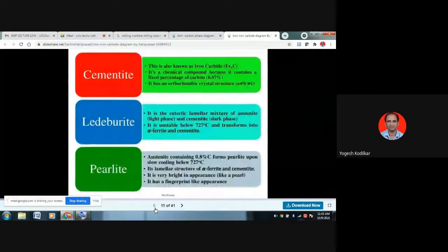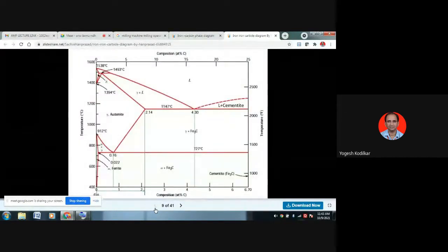This is the iron carbon equilibrium diagram showing different crystal structures. Initially, there is the alpha ferrite phase at 0.08% of carbon. Above 727 degrees Celsius and above 912 degrees Celsius, it is completely converted into gamma austenite. This alpha ferrite is in BCC structure, and at 912 degrees Celsius it is converted into gamma austenite. Above around 1490 to 1530 degrees Celsius, the gamma austenite is converted into delta ferrite, again having BCC structure, and then the liquid phase. This is the allotropy of iron.